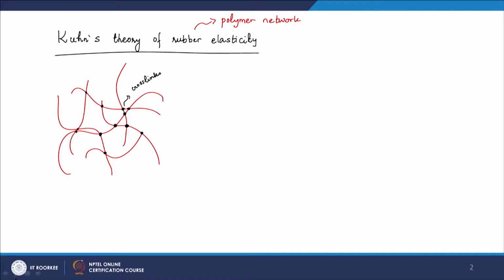And as you can see in the way we have drawn, the polymer strands in the entire network can vary in their end-to-end distance and their number of repeat units, because if you think of how this kind of thing would be synthesized, you put polymer solutions in a beaker, then you add a cross linker, and the cross linker will cross link the polymer chains in a somewhat random fashion.